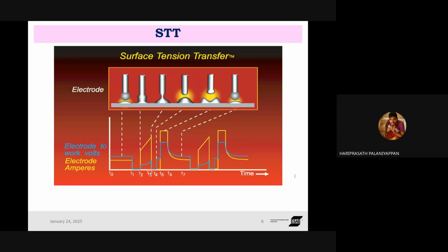Here also we have the same 6 segments that we see in the conventional GMAW process. One thing is you can clearly see we couldn't get any spatter in this process. How did they control this spatter? Through the controlling of voltage and current. Here we can clearly see in the voltage and current waveform, the yellow color indicates the current waveform, and the blue line indicates the voltage. With this, the ball formation is started and then interacts with the base metal.